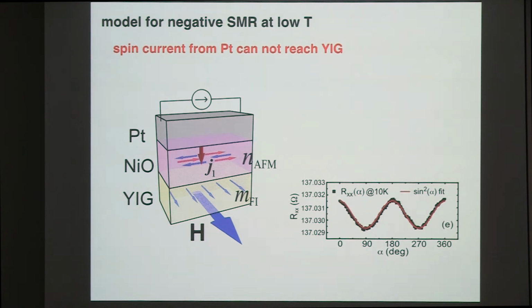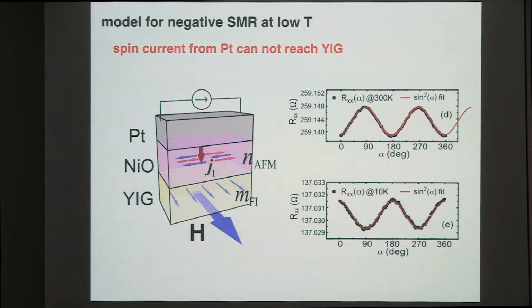But at the same time, if the thickness of nickel oxide is not too large, this nickel oxide can still rotate coherently with YIG. So YIG here actually serves the role of a super big magnetic field, so it can control the direction of the nickel oxide. Because the magnetic field is always perpendicular to the Néel order in nickel oxide under this condition, what you see is that the SMR will have a 90-degree phase shift with respect to the room temperature result. So this is the origin of so-called negative SMR. For a fourfold effect like MR, negative sometimes only means a 90-degree phase shift.